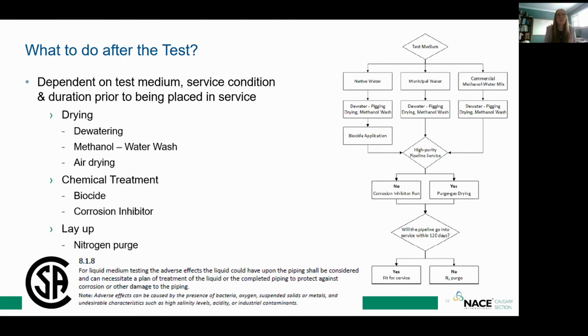You need to make sure that, and for Pembina, we've decided to go with a methanol water wash, not sitting stable there, but just a quick wash to help speed up the drying process to get that accumulated water in those low-lying spots dissolved into that water methanol batch and to remove it from the pipeline. In the cases of native water, it is mandated to use a biocide application. So that way we don't have, and I got a whole bunch of corrosion engineers on the phone, we don't have a bunch of MIC chewing away at our steel.